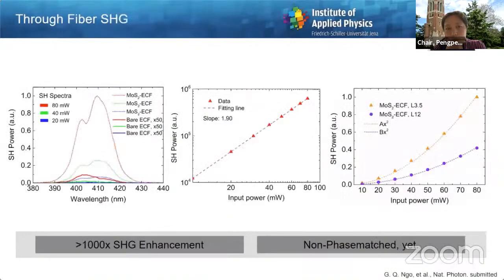The second effect that we looked into is second harmonic generation. And you're probably aware that optical fibers do not show second harmonics simply because they're made of glass, which is an amorphous substance, and therefore it does not have a second-order nonlinearity. Any kind of second harmonic that you actually see in optical fibers, which is usually almost negligible, comes from optical surfaces or from some contaminations. So, and what we've done is we've basically taken our fibers,